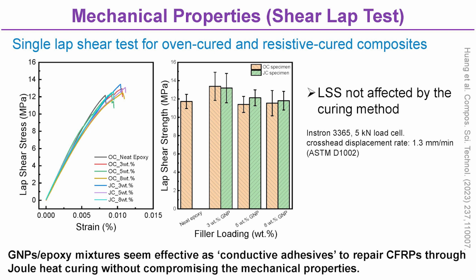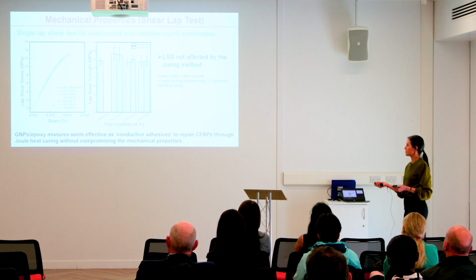We tested the mechanical properties of the bonded joints of the samples cured in the oven and cured electrically by single lap shear tests. And here we see the obtained results. We see that the lap shear strength was very similar in all the cases, independently of the formulation of the adhesive and also independently of the curing method employed. This suggests that these electrically conductive mixtures seem to be quite effective as conductive adhesives to repair composites through Joule heat curing without compromising the mechanical properties.